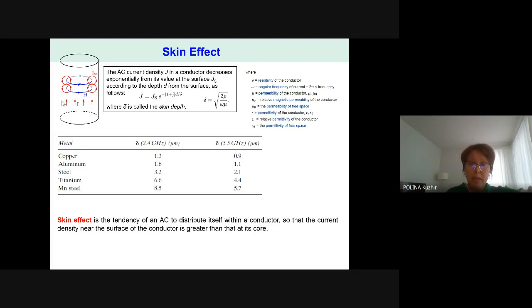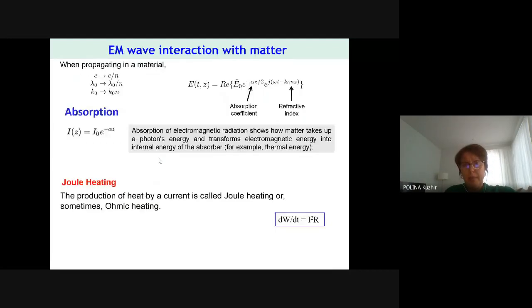At certain frequencies, like for X-rays, we will have almost invisible skin depths for most known conventional metals. If we compare the skin depths for, say, copper at two different frequencies, 2.4 and 5.5 gigahertz, you will see that the electromagnetic field could penetrate into the copper up to 1.3 microns at the smaller frequency, and less than 1 micron at the higher frequency.